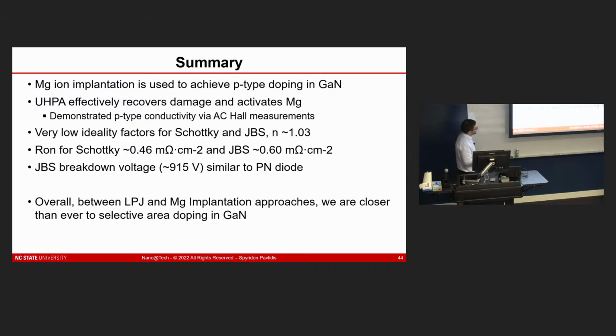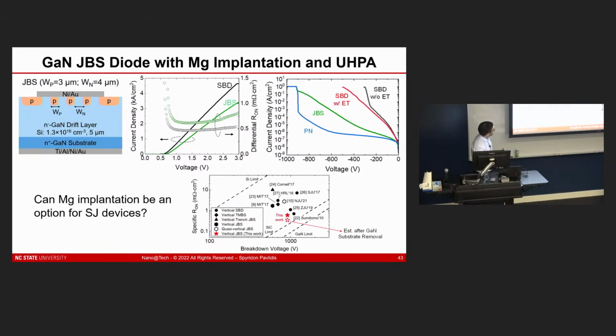And so overall, between the LPJ and the magnesium implantation approaches, we're closer than ever to selective area doping in gallium nitride. If we make these super junction devices scaled up to higher voltages, I think that could be a real game changer in the power field, especially because we can do this at scaled approaches that could really go beyond what silicon carbide is able to do with more conventional cases. And now we're even unlocking JBS diodes at high voltages, which I think will be very, very promising for next generation electronics. And the last teaser that I have here, which is something I skipped over, is this question of can magnesium implantation be used for superjunction devices?